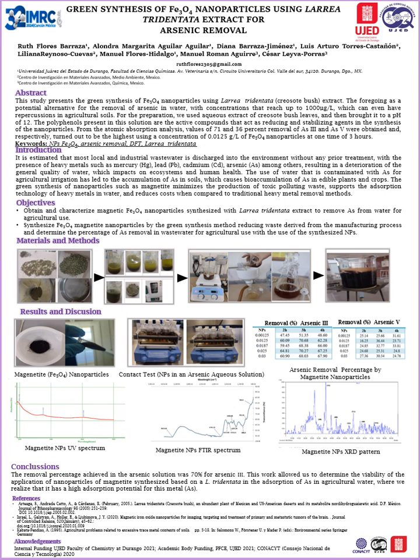This process is repeated 3 times until the solution reaches a uniform crystalline green color. Afterwards, a second wash of the plant is carried out with deionized water in a 1:5 ratio, which was done twice to remove the residues of hexane that remained in the plant solution. Lastly, we take all the precipitate and filter it, and then set it to dry in the oven at 60 degrees Celsius for 8 hours.